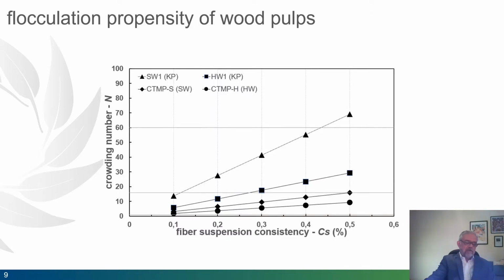Now let's see the results of crowding number and relative formation evaluations of traditional tissue paper furnish compositions. Let's start with the flocculation propensity of wood pulps. The crowding number increases linearly with increasing fiber suspension consistency, but in a more pronounced fashion for some of the pulps. In general, the crowding number values of the selected pulps were found to be between 1 and 60 in the interval of consistency considered, from 0.1% to 0.5%. That is, in semi-dilute suspension regime where fiber collisions are forced, representing a certain risk of flocculation. In particular cases, crowding number values above 60 that fit the fiber suspension concentrated regime were found.